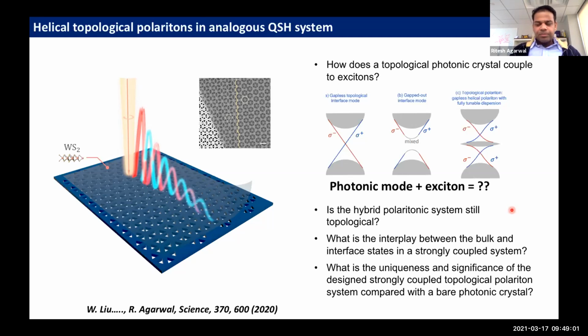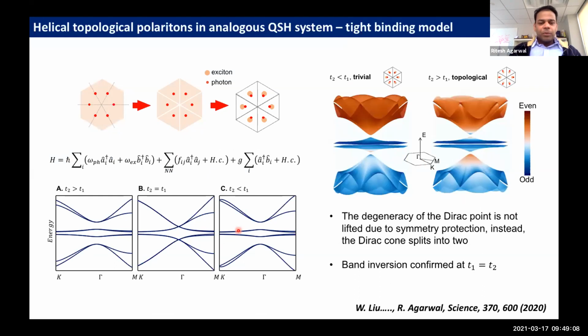So we had to do a lot of calculations, and develop, I would not say fundamentally new theory, but protocols that work for this polaritonic system. One thing was very clear: at least in this regime where we have a photonic crystal which is topologically non-trivial, we have to have excitons which follow the symmetry of the system, and they should be isotropic in terms of their polarization properties. So these red particles are excitons or photons, and we assume a homogeneous distribution of excitons. At each unit cell that we define, we have an exciton and a photon following the same symmetry properties of the underlying lattice. So the excitonic material, at least in our step one, first demonstration, does not break any of the symmetries.